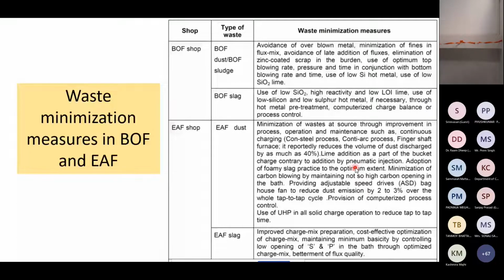Even you can see the slag generated in the electric arc furnace: improved charge mix preparation, cost effective optimization of the charge mix, maintaining the minimum basicity. Because we are adding an alkaline material, that is lime, proper basicity should be maintained, and basicity should be properly controlled. So you can see that the entire idea is about skill based operation.